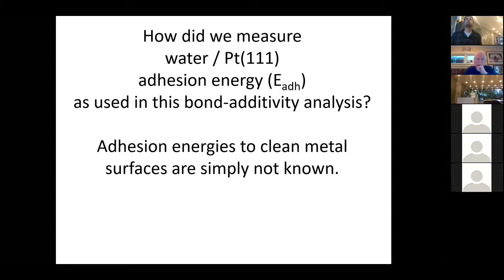But it's more complicated in the gas phase, because you have to crank the temperature up. And by the time you get up hot enough to be desorbing these 200 kilojoule per mole or 150 kilojoule per mole molecules in the gas phase, you start breaking carbon-hydrogen bonds, and you build up heavily dehydrogenated species.